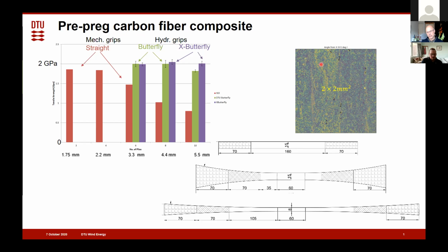It's a prepreg, so we have a layer structure, which you may be able to see here. So we have tested this sample, adding more and more layers from 3 plies to 10 plies, and then used 3 different geometries to test that. If you take the rectangular test sample first, that is the red columns here, when the sample gets thicker and thicker, with more and more plies, we can see that at a certain point our strength of the material will decrease.